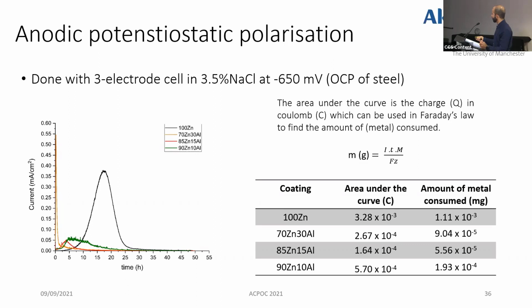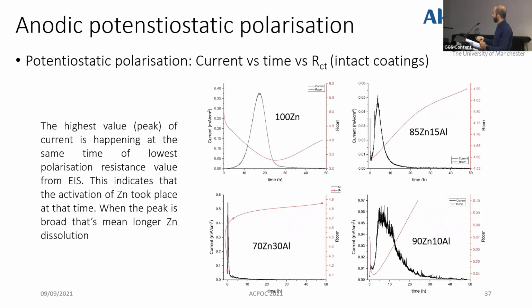So the first one appears for the 100 zinc, and then for the 90 zinc 10 aluminum, and then for that one, which is 85 zinc 15 aluminum. Also, the highest value, the peak of the current, is happening at the same time as the lowest polarization resistance, which indicates that the activation of zinc took place at that time. When the peak is broad, that means longer zinc dissolution, and the broader peak here, I think, is for 90 zinc 10 aluminum. That means longer dissolution, or the galvanic action is prolonged by the addition of aluminum in this coating.